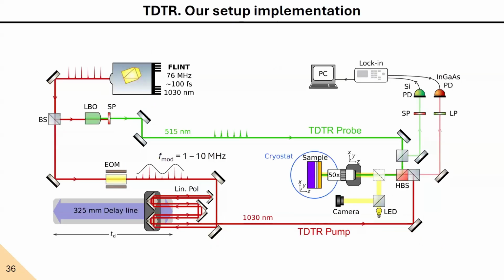And how does this look like in our lab? Well, we have a fundamental laser that emits laser pulses centered at 1030 nanometers. We split this laser in two lines, and we use a second harmonic crystal to frequency double our probe beam, so we make it green. The pump laser goes through an electro-optic modulator, and we produce a sinusoidal modulation of its amplitude in the frequency between 1 and 10 megahertz. This beam goes over a mechanical delay line, which introduces our control time delay between pump and probe.